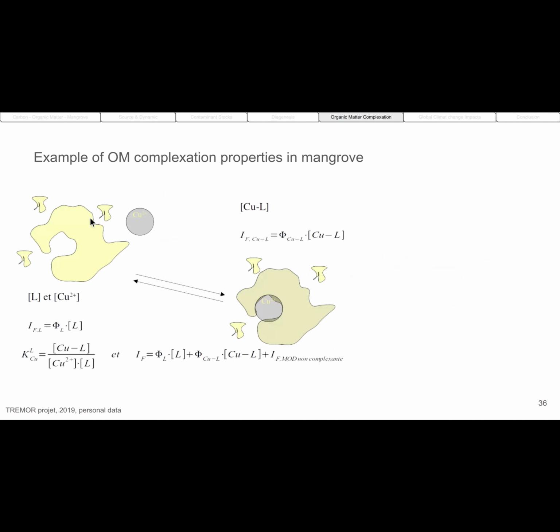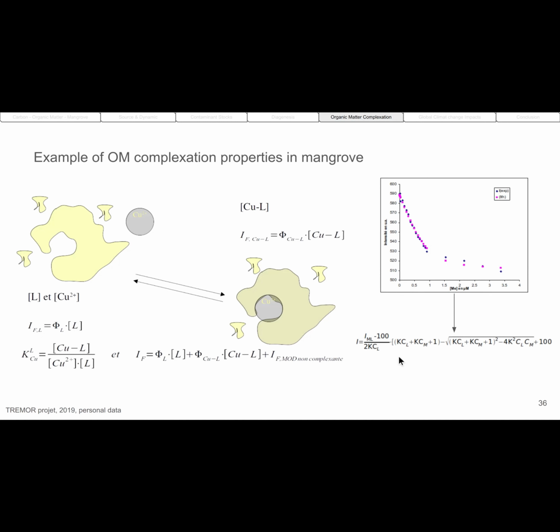The principle is this: organic matter has fluorescent property and a quantum yield of fluorescence. And when this organic matter associates with metals, the quantum yield of fluorescence decreases. So if you consider that there is an equilibrium between organic matter and metals, with this constant, a quasi-thermodynamic constant, and that there is a number of sites of complexation, you can fit these two parameters, number of sites and constant of complexation. You do it by adding the metal little by little, and by adding the metal, you have a decrease of fluorescence. By using the model, you have an equation, in fact. And this equation, once it's fitted, gives you the constant and the capacity of complexation, which is the number of sites per gram of carbon.